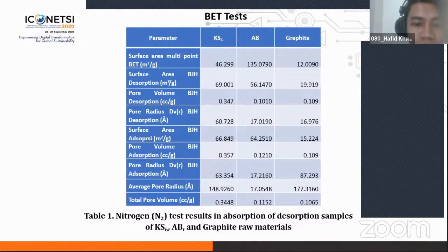The acetylene black or AB raw material is also compatible with graphite crystals, but slightly different in the crystal structure. Its peak is not as high as that of the KS6 material, indicating less crystallinity. In addition, the XRD test result shows graphite is also compatible with graphite crystal with a very dominant peak at a 2 theta diffraction angle of 27 degrees. No impurities were detected from all the starting materials, which concludes that the raw materials have high purity and further measurement and evaluation of cell performance can be purely referred to the material only.